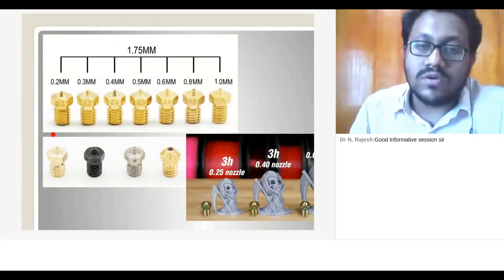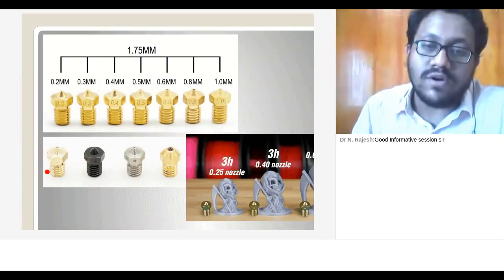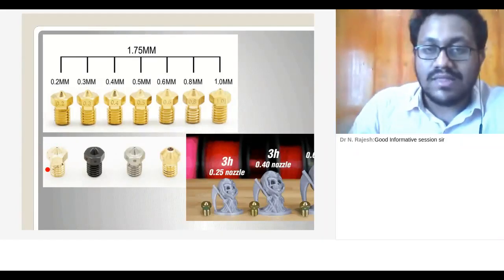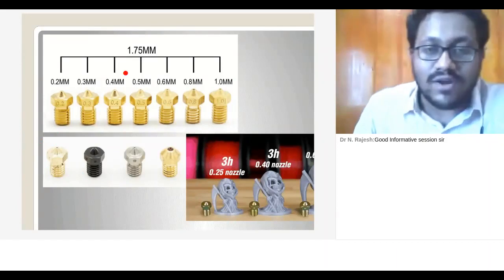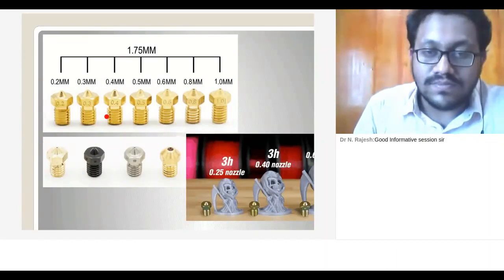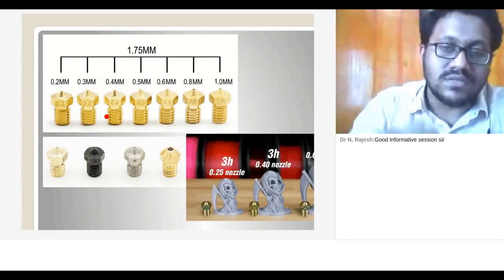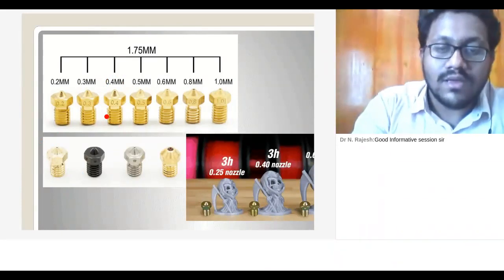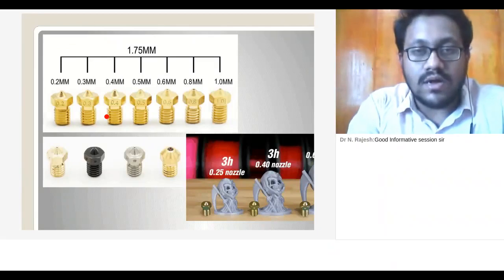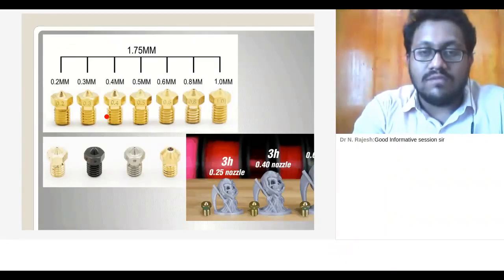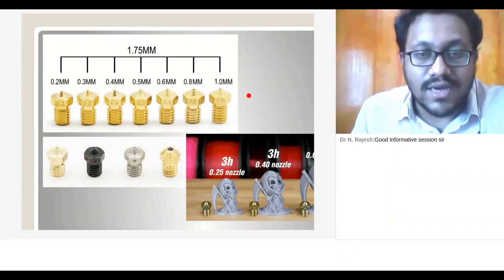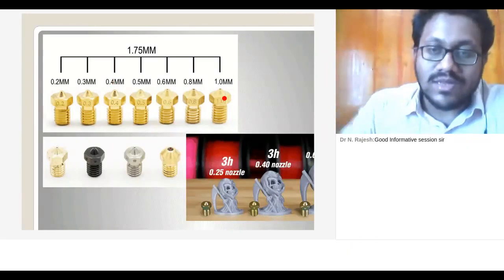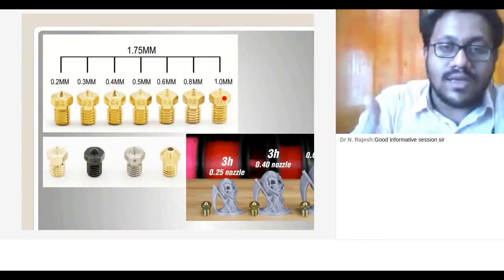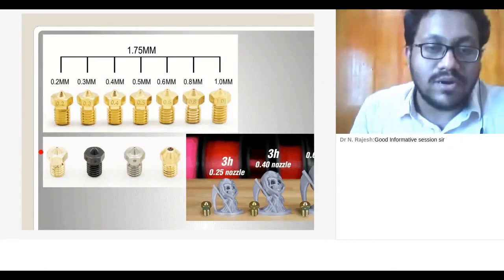So if you are using a brass nozzle for a carbon fiber filament, say, for example a 0.4 mm brass nozzle, once we start using the carbon fiber filament, after a few prints or 2 days of time, the nozzle gets worn and it gets converted into a 1 mm nozzle. So there is a lot of wear happening in a brass 3D printer nozzle.